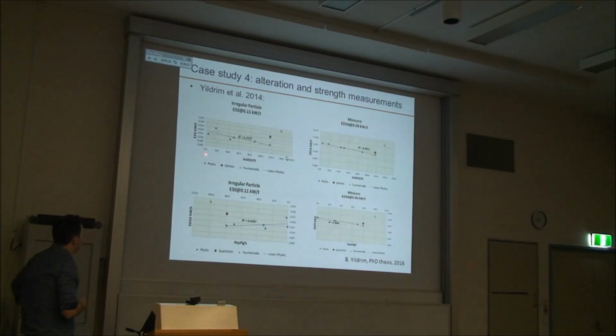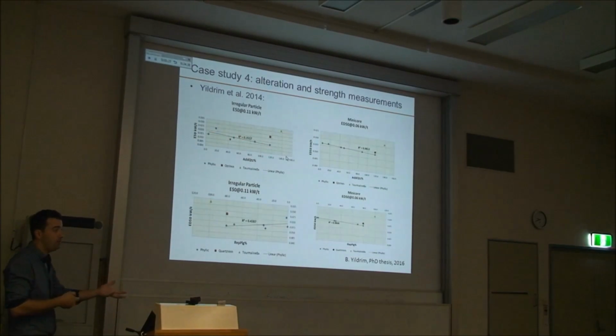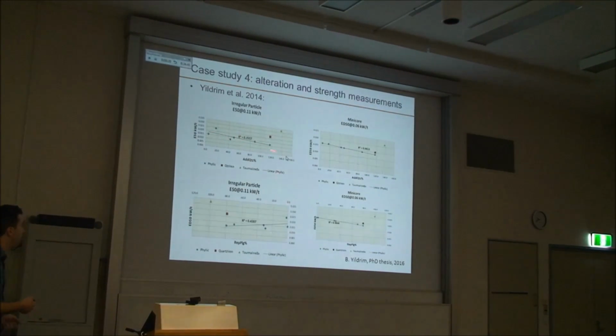So on the left side, you can see the correlation between the E50, so the breakage properties, and the alteration. It looks like there is a relationship, so it's getting softer, or the E50 is reducing when the alteration is increasing, and the same case here, but you can see that the correlation factors are quite low, and that using the irregular shaped particles, he wasn't able to actually differentiate the distribution. So that's what I showed before, where the distributions are actually very close to each other.